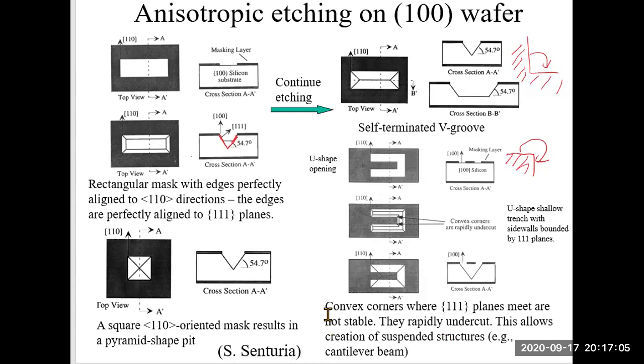Then the convex corners, where 111 planes meet, are not stable. We know that this plane and this plane are both 111 planes, so this convex corner is where these two 111 planes meet, and this convex corner is not stable. So these two convex corners will be rapidly undercut. They will be attacked, they will be etched. And this allows the creation of suspended structures, for example a cantilever beam. So this masking layer becomes freestanding, a cantilever beam.